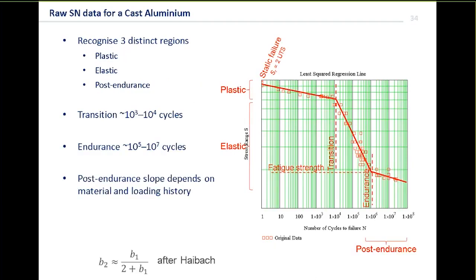So when we look at these typical data then, we find that they fall into these three distinct regions. At the top, there's the plastic region, there's the elastic region in the middle, and then there's the post-endurance region after that. And they're characterized by two transition points. The transition life is the one that differentiates between plastic and elastic. And typically this lies somewhere between about 1,000 and 10,000 cycles to failure for most metallic materials. Further along than that is the endurance limit. So this is either the endurance, the infinite life one, if you've got mild steel under constant amplitude loading, or in aluminiums we call it the endurance limit simply because there is a change of gradient. And they're typically lying between about 10 to the 5 and 10 to the 7 cycles.